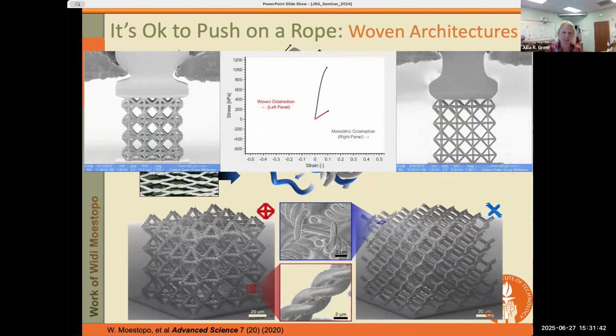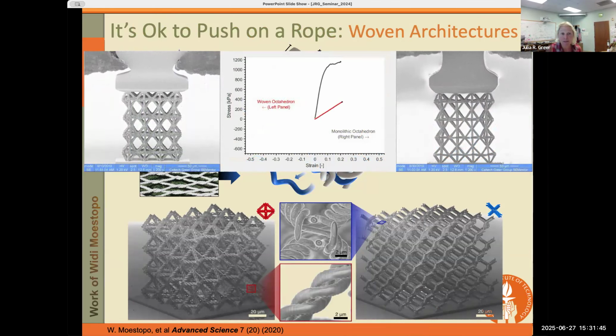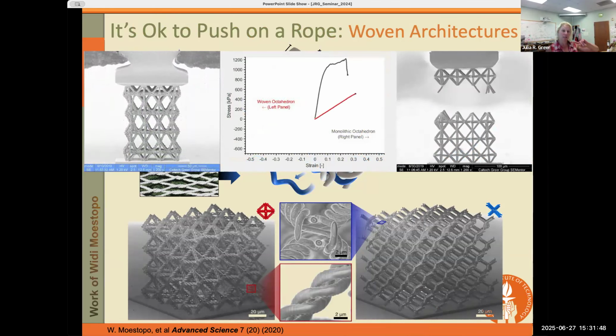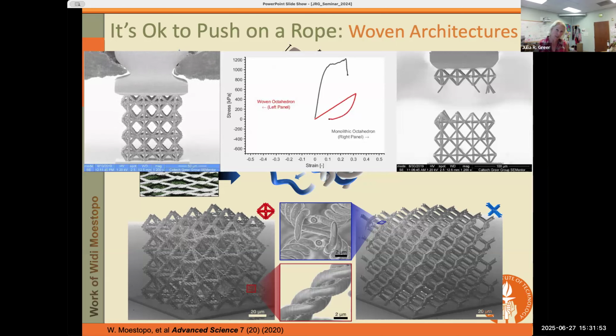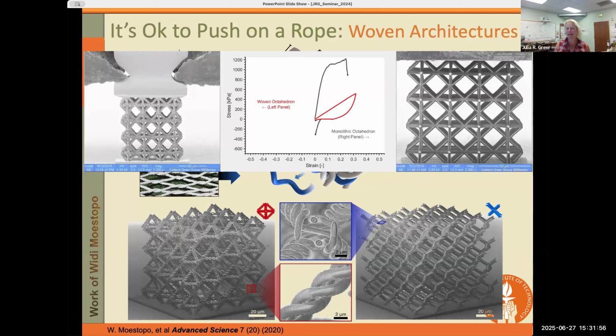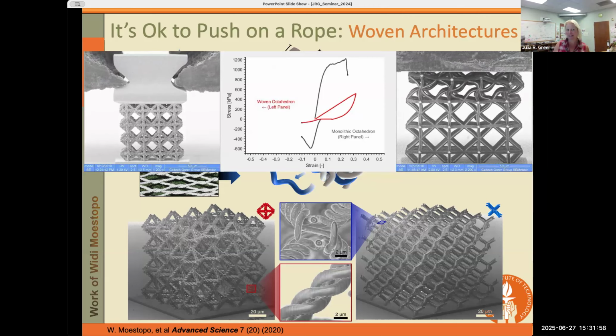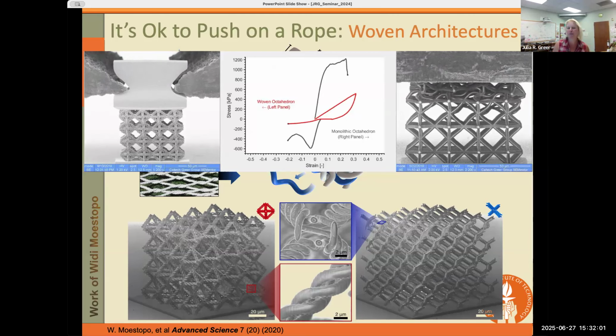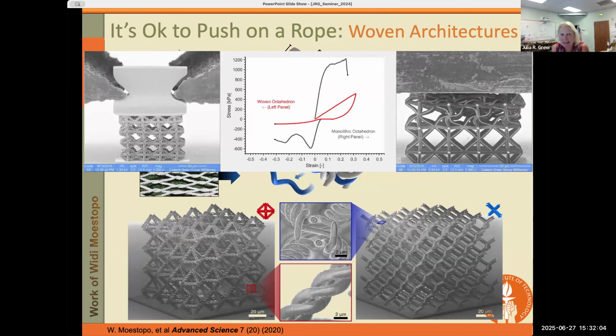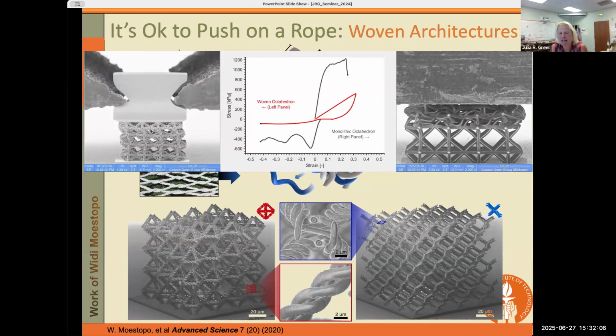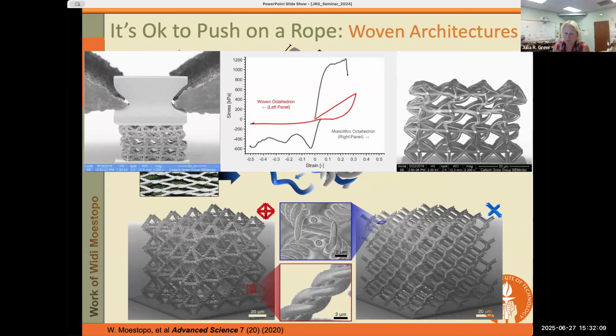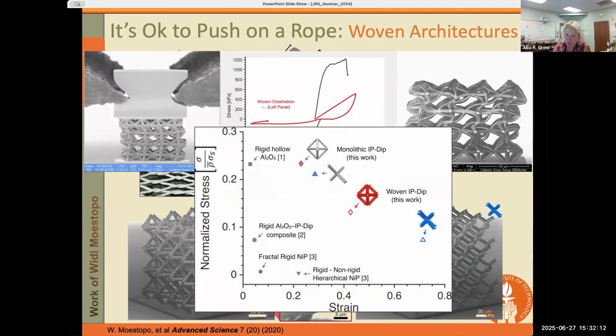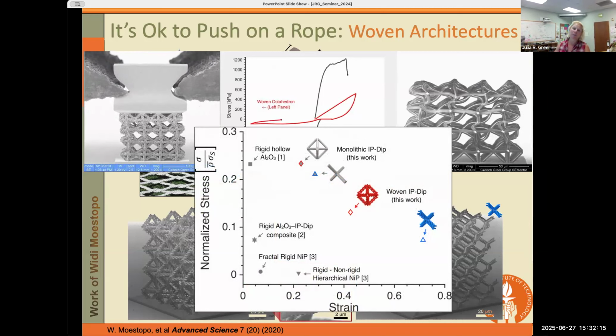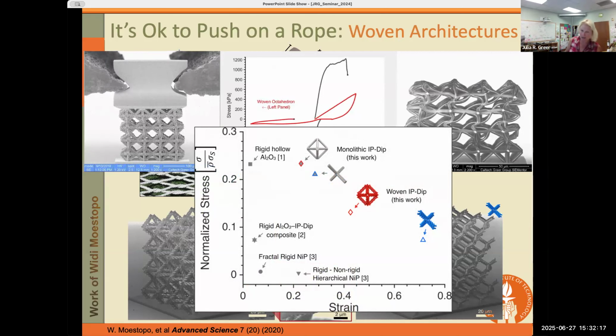And so what we're showing you here is the side-by-side comparison of the tensile deformation of the woven nanolattice. So you can see that on the left, it's very, very extendable. Well, of course, the regular nanolattice on the right broke. And because the original one didn't break, we can do the compression experiment on exactly the same specimen, which is not true for the specimen on the right. And you can see it compressing, both of them compressing, and you can see how much more energy this material is able to absorb. So what we're learning is that the interwoven approach, where you do away with the nodes, which of course are the culprits for damage accumulation, you can get to much greater strains and make much more compliant materials.